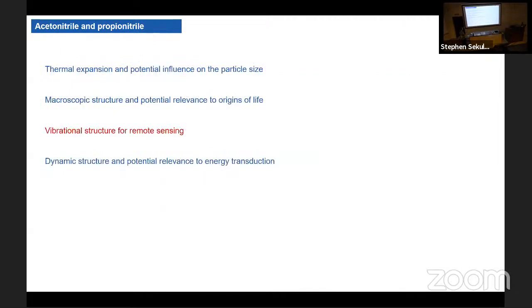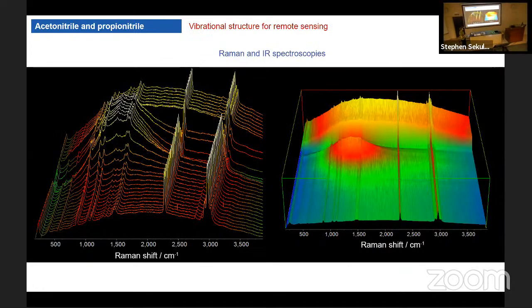Next, vibrational structure. As I said, I mentioned a couple of times why vibrational structure is important, and we do research in that direction too. What we did is we collected the Raman spectra. These spectra were collected at Argonne National Lab with a Raman probe. There was just remote sensing, so the quality of the spectra is not very good. We're not really able to tell the difference between different polymorphs and between the co-crystal and so on, because our data was not very high quality.